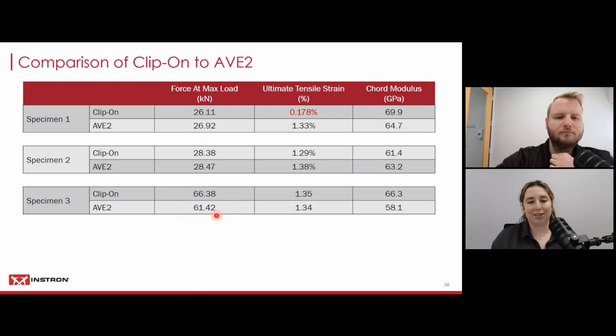Composites, as we've said, are influenced by vertical alignment. I could have aligned it wrong. I could have changed my clamping pressure. You're going to have some variables in there that change that. But what we care about right now are the ultimate tensile strain. For specimen 1, I pointed out that 0.178% is probably wrong. So it's very likely closer to that 1.33%.